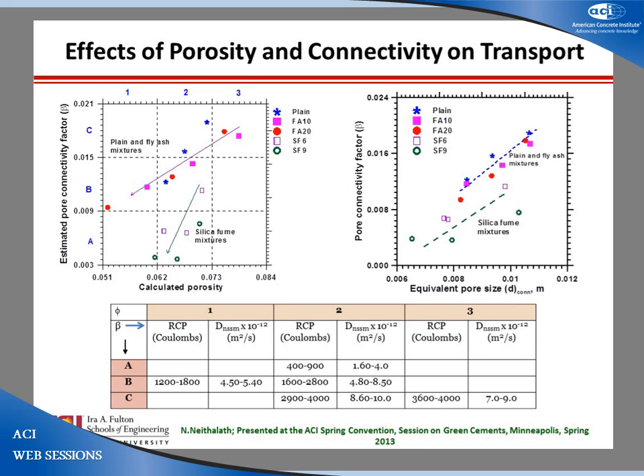So the basic idea is that if you go down from 3 to 1 this way, where you reduce the porosity, your transport values really don't change that much. But if you go this way, where you reduce the pore connectivity, you can see the non-steady state migration values going from 8.6 to 1.6. So pore connectivity is more important in transport, and pore connectivity is more influenced by the pore sizes than the porosity. And these are all from model based results.